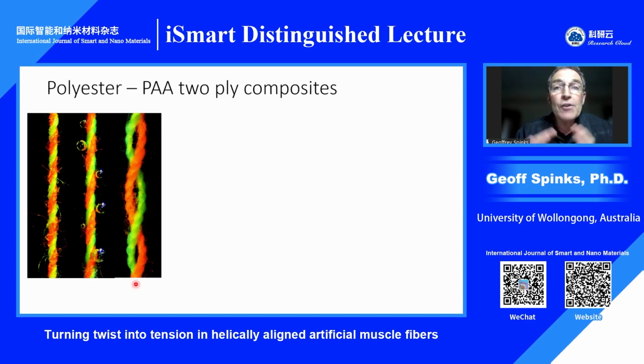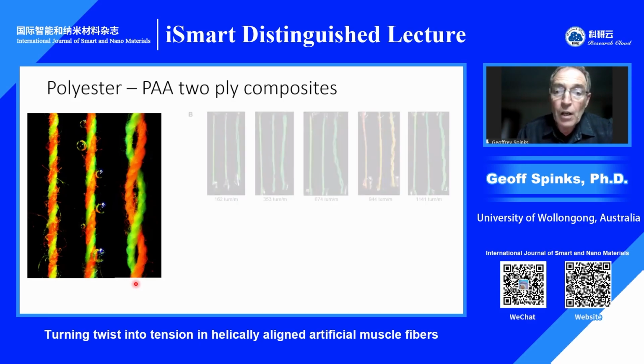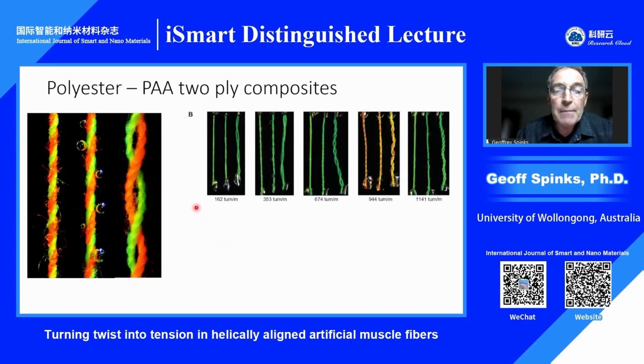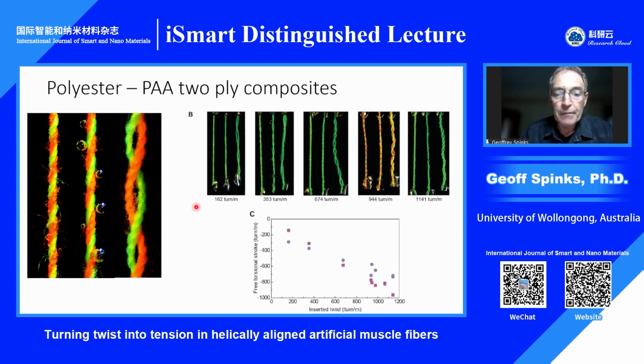So the free swelling allows torsional untwisting and obviously an increase in diameter. I was able to produce samples made with the same materials but prepared to different inserted twist. The cross-linking of the polyacrylic acid locks that twist into place, so it's permanent. And then the swelling causes it to untwist, which can be reversed by deswelling. We measured the free torsional stroke, or how much rotation is occurring with just one end clamped while it's swollen in acid and base solutions, and plotted that against the amount of inserted twist.